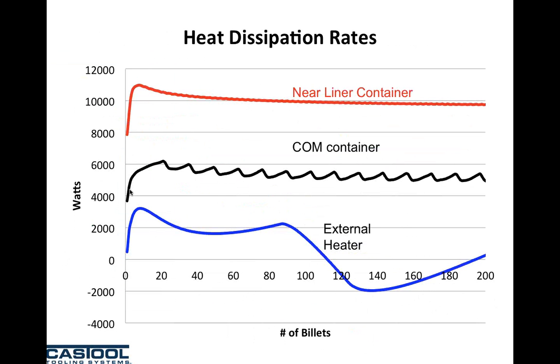So that's why you see a lot of containers, as they extrude, the temperature of the liner starts to creep up because the container doesn't have the ability to dissipate the heat. And obviously, the blue one is the worst one, which is the external clamshell type. You have positive and then goes to negative. So you take away heat and you supply heat to your liner and to your billet as well.